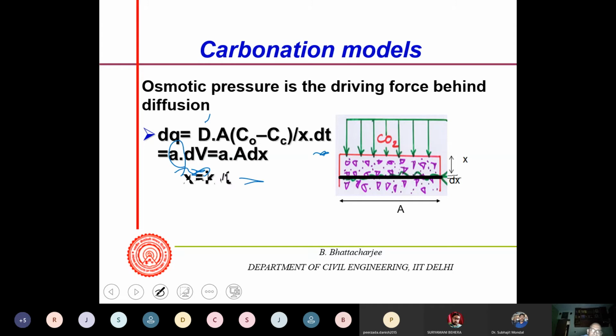And if I integrate both sides, I'll get x k root t. You know, A dx, A will cancel out. And I'll have x coming here, dt here. So some constant into t dt is equal to x dx. So x square by 2 into some constant, one can write that kd. So by integrating, I simply get this. So you can see that depth of carbonation is a function of root over time.